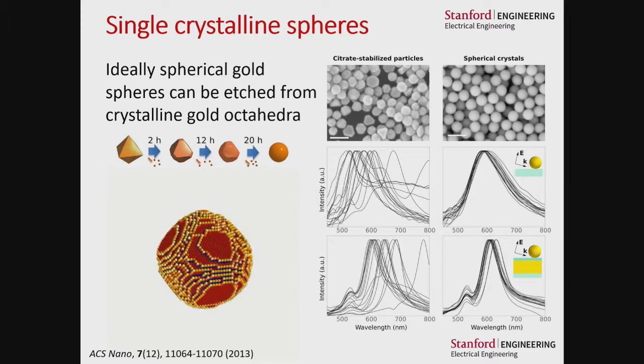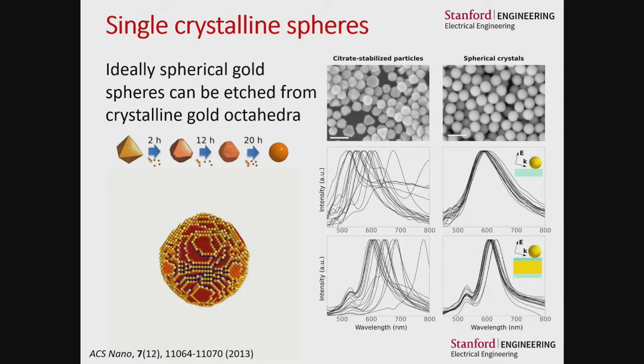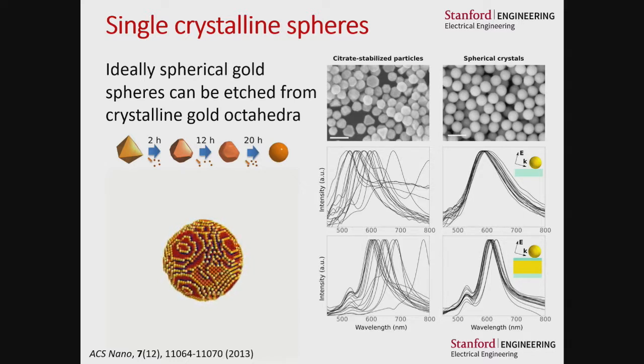So here we can see that traditional citrate stabilized gold particles tend to be highly faceted because of the surface energies of gold. But in this case, we have really smooth spheres, and they're extremely monodisperse. We've characterized them and done a lot of measurements. They're extremely reproducible. So chemistry certainly is a really good route to get extremely high-quality plasmonic materials if we're not trying to make well-defined structures by lithography.